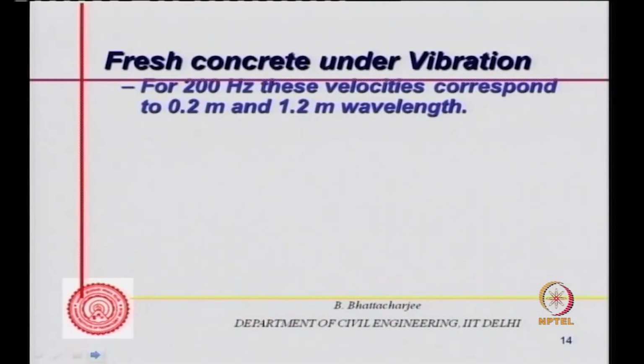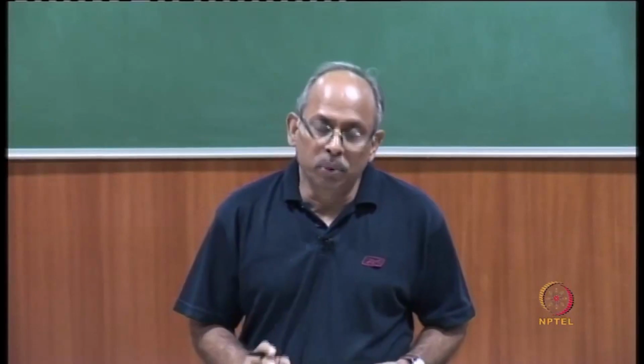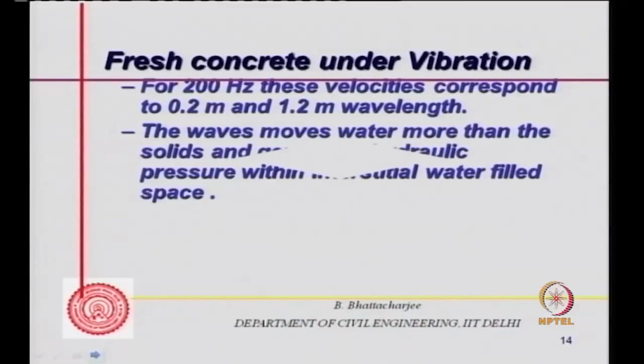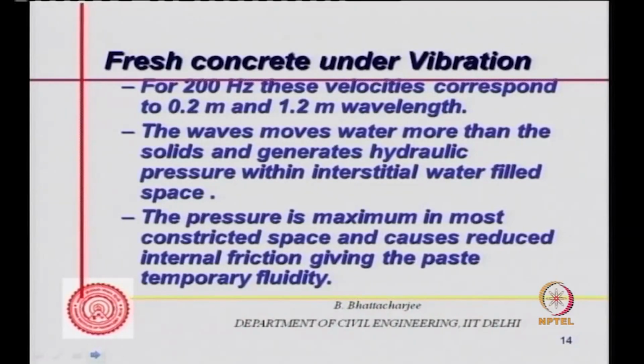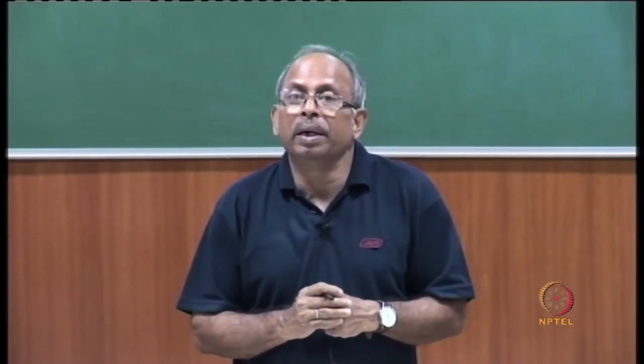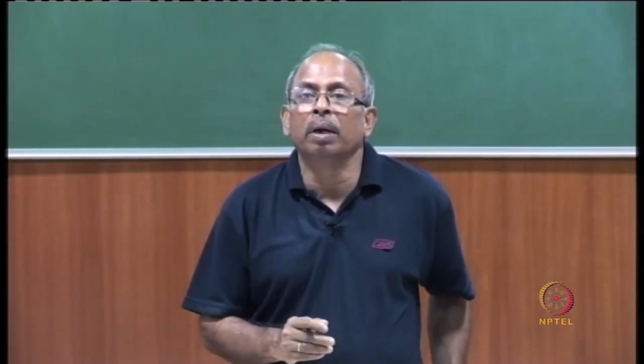For 200 hertz, the wavelength is of the order of around 0.2 meter to about 1.2 meter. The waves move water more than the solids, and generate hydraulic pressure within the interstitial water-filled spaces. And this pressure is maximum in the most constricted space and causes reduced internal friction, giving the paste temporary fluidity. So this water within the constricted space, because of the movement, exerts pressure, and that overcomes the friction. And that's how the particle moves.